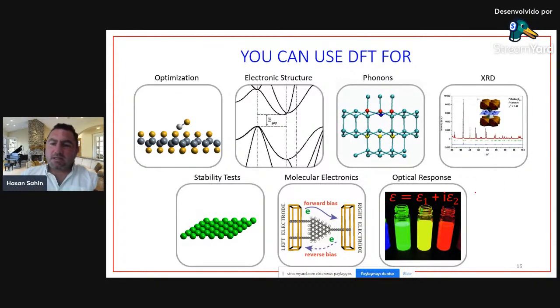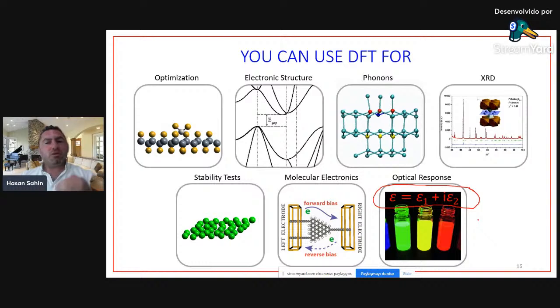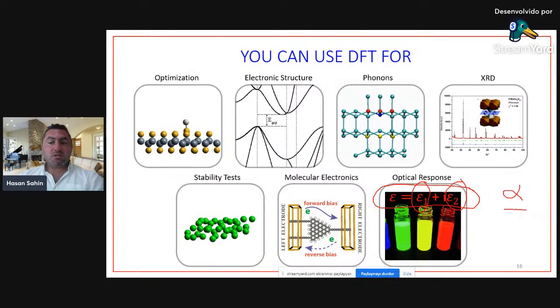And if you are able to calculate the dielectric response of a material, whether it is a crystalline or molecular structure, it doesn't matter, then using the real and imaginary parts, you can get the absorption coefficient alpha, or transmittance, or reflectance. All of them are possible, and it's easy. So by using DFT, you can calculate the optical response of materials.